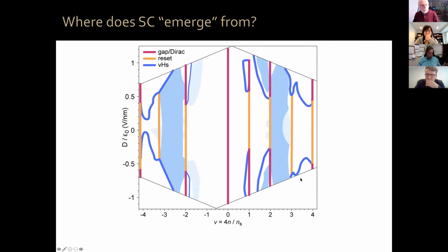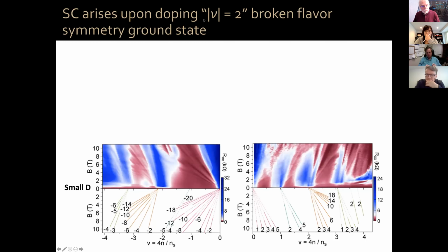So where does the superconductivity emerge from in the system? Okay, so you can see that at low displacement field, it's in between these two resets at 2 and at 3, okay? And at high displacement field, it's bounded by van Hove singularities and this gapped Dirac, okay? So the superconductivity arises upon doping the nu equals 2 broken flavor symmetric ground state. What does it mean?